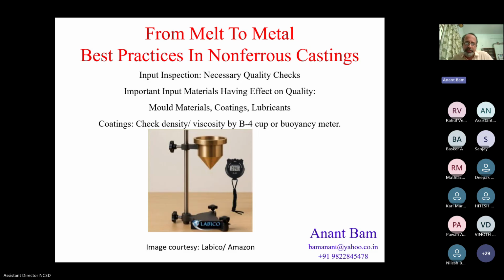So usually it is expressed in seconds. Say B4 cup timing 18 seconds, 20 seconds, 24 seconds, like that. If it takes less time, that means your coating is thinner. If it takes more time, that means your coating is on the thicker side. The thickness or viscosity of the coating is a function of the quality and the desired effect which you want from the coating.